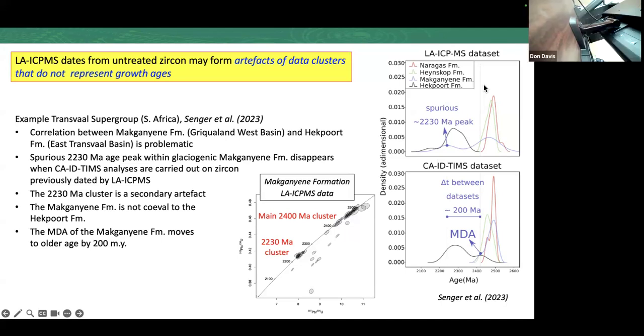Anyway, this all occurs because lead is highly volatile, of course. So when you ablate the sample, you form an ablation cloud, and you separate the lead from the uranium, and the uranium condenses in the melt globules, and those go right into the ICPMS. Whereas if any material becomes trapped against the walls of the pit or around it due to fallback, that will be essentially depleted in lead, but contain uranium. So of course the excess lead goes into the signal, and that's why it continuously grows. I've been trying to model this for about a year now, and it's really complicated. It's tearing my hair out trying to figure out exactly what is the best way to calibrate this.